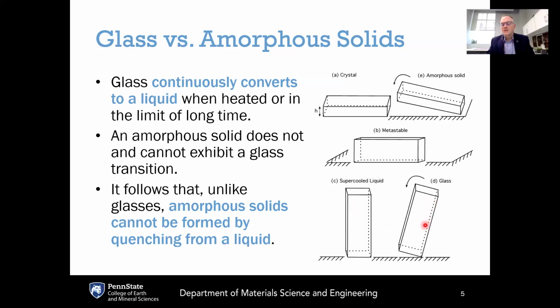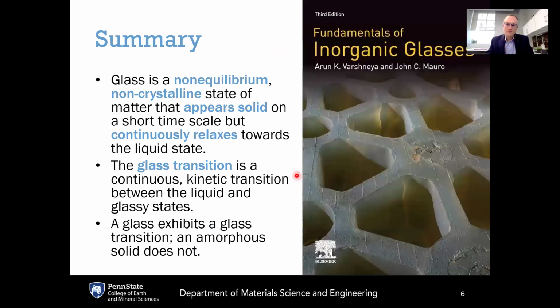So the glass is unstable with respect to the supercooled liquid, and the supercooled liquid is metastable with respect to the crystal. The amorphous solid is unstable with respect to the crystal, meaning that as an amorphous solid relaxes, it is not relaxing towards the supercooled liquid state, but rather it is relaxing towards the crystalline state. So it is a different type of disequilibrium compared to the glassy state itself.